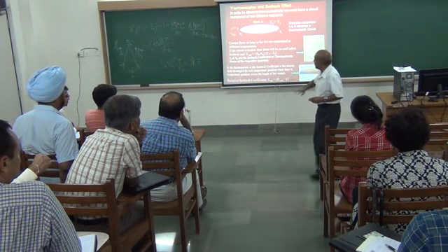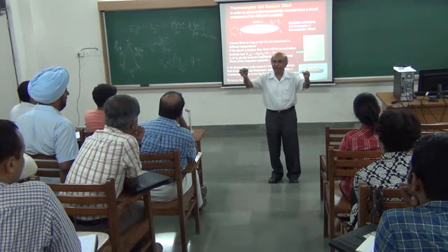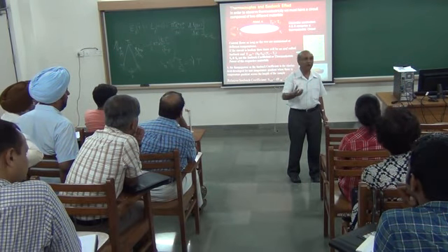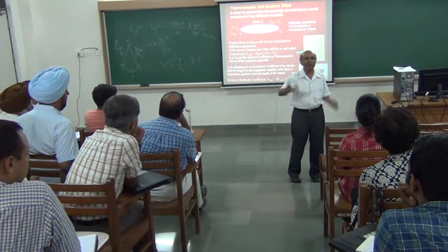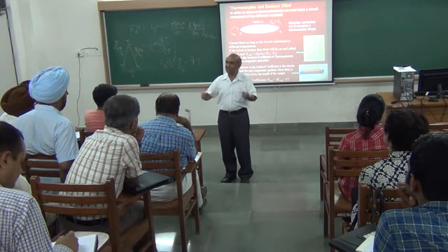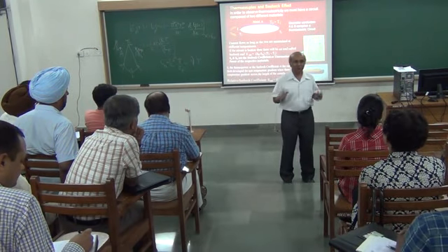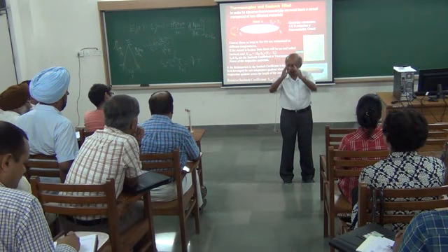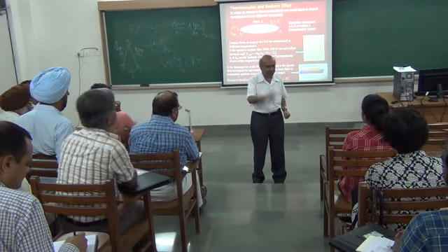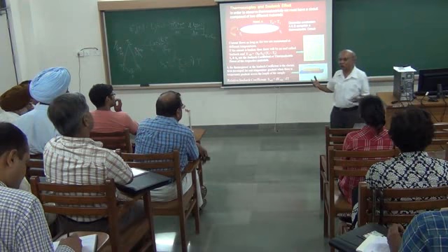So, having come to that, this part of the complete symmetry. In superconductors, even though I create a temperature difference, the electric field is 0. What it means is that S, the Seebeck coefficient of a superconducting state, is ideally 0. It is my reference. A superconductor is a perfect state in which even if I create a temperature gradient, it does not produce an electric field. I use that as an ideal reference. So I will make a junction of a superconductor with my material A. What I measure is eventually that of my material A only, because the other one is 0. That's how we can calibrate.